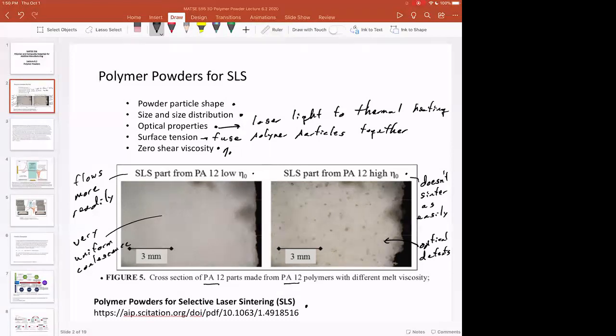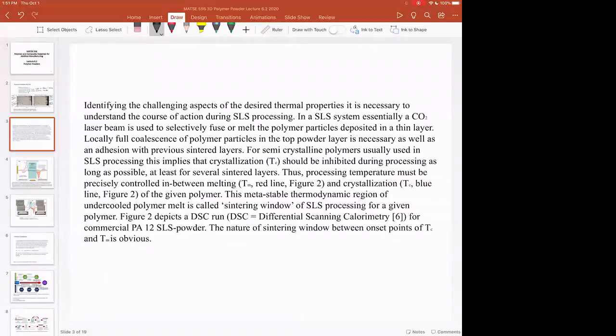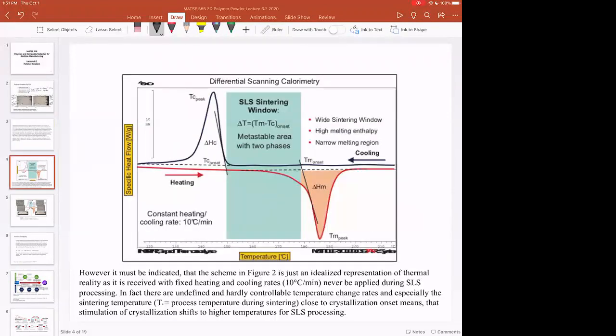So these are some important things to remember as you start to design or select a polymer feedstock for your polymer powder in SLS. Now, one issue with this is that there's lots of different things going on in terms of the crystallization and the speed of processing. So this paper right here is where this SLS sintering window is from. And remember, this is in differential scanning calorimetry, and the heating rate in DSC, at least for this one, is 10 degrees C per minute heating and cooling.